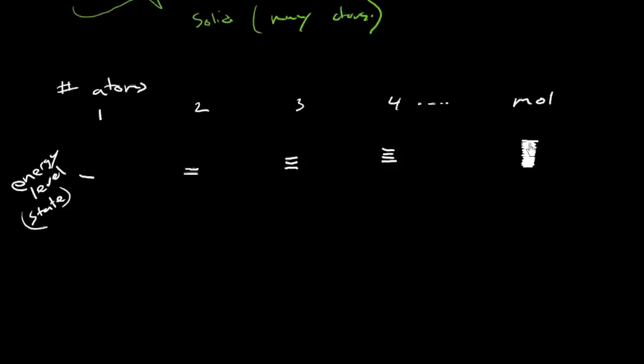They're not exactly the same energy. And if you go to three atoms close to each other, you'll have three states, four atoms, you'd have four, and so on. Well, what if you had a mole of atoms? Well, I'm going to have to draw a mole of possible states. And I'm going to be here for a while. OK, I'm not actually. I'm going to just draw in a bit. And you get the idea, right? These, if I were to draw 10 to the 23rd lines here, it would certainly be solid.